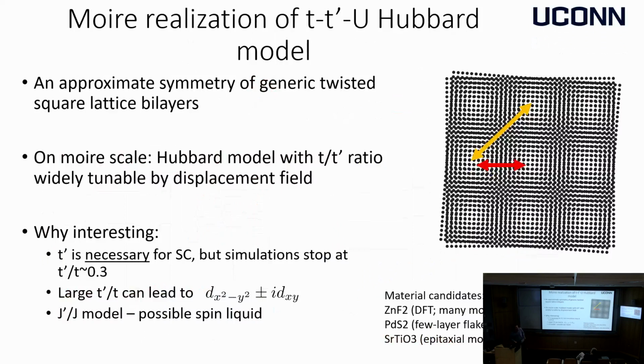Why all of this may matter is that if we had interaction, we would have a Hubbard model where you can tune the ratio between nearest neighbor and next nearest neighbor tunneling. That turns out to be a super crucial parameter. Without next nearest neighbor tunneling, there's no superconductivity. Old numerical simulations conservatively go up to 0.3, so T prime is smaller than T by almost 3 times.